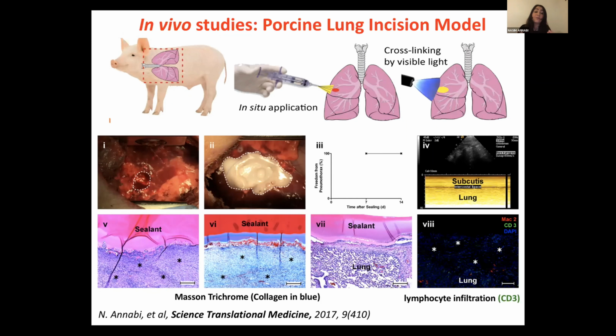And our next step with this project is how we can use it to basically seal larger defects under extensive bleeding with this material. And then we use different models like liver bleeding model, we use heart model, and we learned that in addition to adhesive properties, we need to modify the material in a way that it also have hemostatic properties. So we not only seal the defect, we also control extensive bleeding once we apply it on a different type of organs with different sizes of defect in the body. And this is our ongoing project at UCLA.